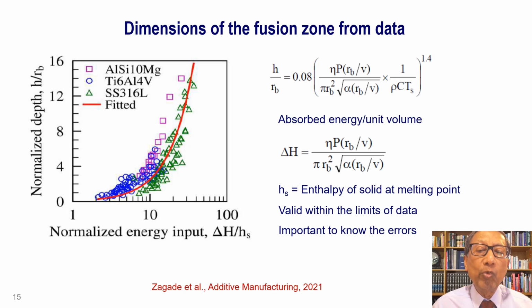So when we have this value, delta H by Hs, we can then read off from the y-axis the depth of the fusion zone. Similarly, we can use another expression to obtain the width value of the fusion zone. And then we have our model for the lack of fusion number, so we can obtain the extent of lack of fusion using this model.